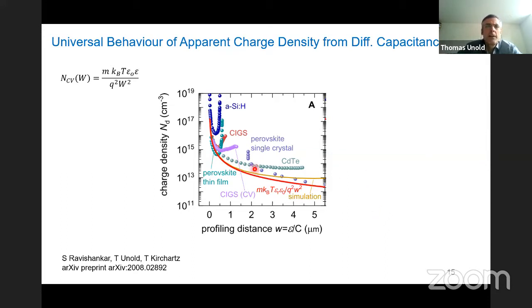And so we looked in the literature and plotted these all in one plot. So here's shown the charge density, here's the profiling distance. So you see amorphous silicon, you see CIGS, you see perovskite, cadmium telluride, CIGS again, perovskite thin film. And they basically all follow this shape here. This red one is this analytical shape. And this orange one is the simulation.